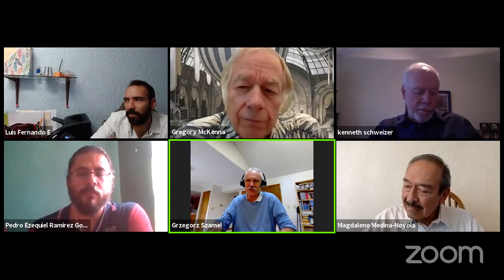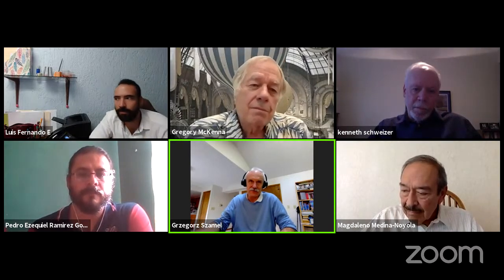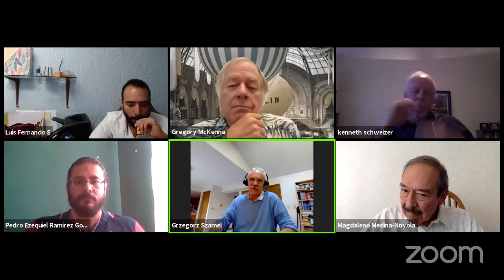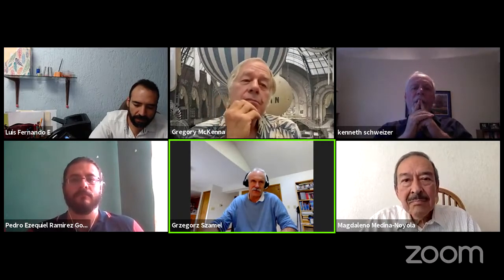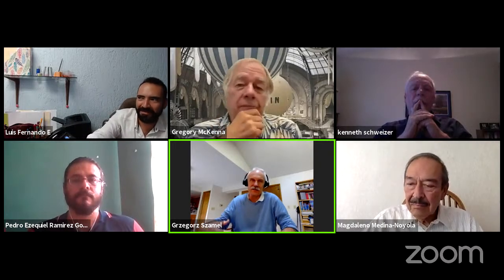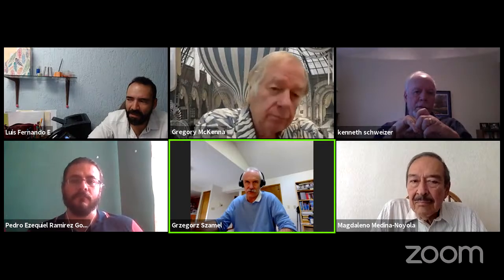And then, okay, so now I have a question to Greg, and that relates to his absolutely amazing Amber experiment. And the question is prompted by what we do in computer simulations when we try to decide whether the system is or is not equilibrated. Typically, we do not look at just, for example, average energy, and check whether average energy approaches its equilibrium value, but we also look at other quantities, because from experience we know that if you look just at average energy or density of the system, then they may approach equilibrium values, but the system is not really equilibrated, in the sense that, for example, if you look at time-dependent fluctuations, they may depend on where you measure them along your simulation trajectory.